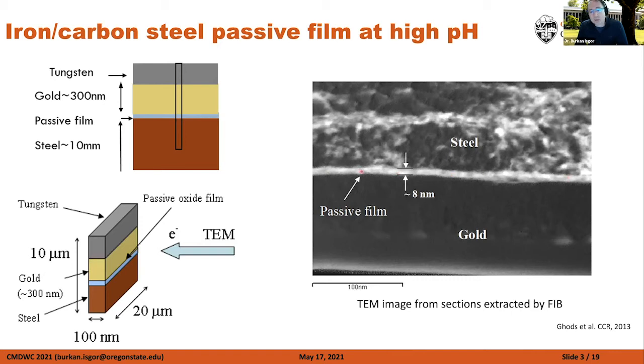This is a passive film that formed on steel surface after about 2 weeks of immersion in a simulated pore solution. The thickness shows here about 8 nanometers. This is actually thicker than the actual thickness because you're looking at a 100 nanometer thick electron transparent sample, so you're basically capturing the valleys and the hills that occur on the surface. And then the actual thickness seems a little bit narrower.